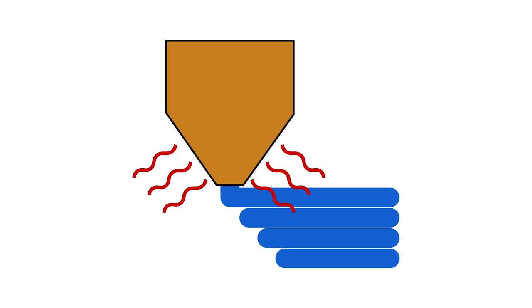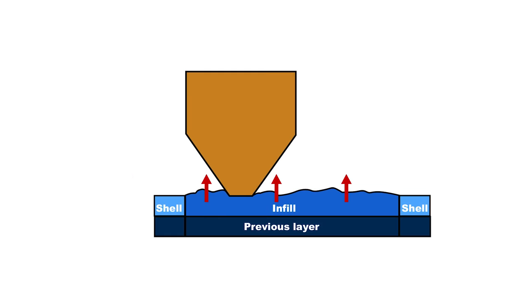Now, the other thing I see people doing, and I strongly disagree with, is printing completely solid miniatures. This works against you for a number of reasons, and we'll go through each of them here. The first is, none of us has a printer whose extruder is tuned to a perfect 100% extrusion rate. It's not possible. This is an analog process. The slightest deviation in filament width, among a host of other reasons, means you cannot reliably print 100% extrusion. You can get very close tuning it, but it will never be a dead 100%.